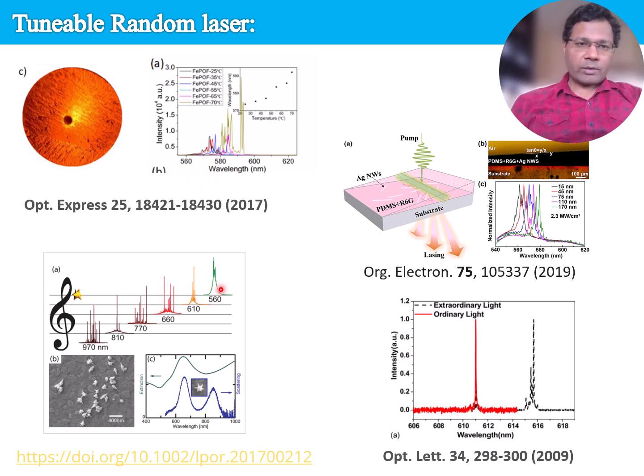Broad spectral coverage from visible to infrared light has also been demonstrated using gold nanostars suspended in dye solutions. These nanostars act as broad scattering centers and form randomly distributed resonators that support coherent lasing modes. This type of system exhibits a narrow emission linewidth below 0.1 nanometer, confirming that gold nanostars provide highly efficient coherent feedback over a wide spectral range.